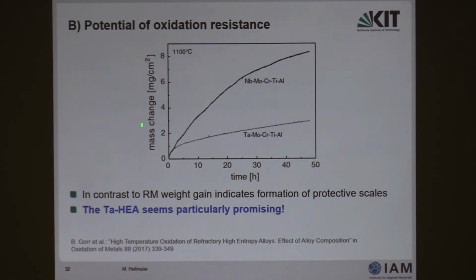We plot this on a quadratic scale. So it's delta m square, so the mass change per unit area to the square, over time linearly. And then you would see that both of these alloys show a linear behavior. And this is an indication for a parabolic growth law. And again, this is another indication that the oxide is protective. You can also have much stronger increases, linearly, for example. Linear oxidation would mean if I double the time, I have twice as much mass change. Or in other words, twice as much metal consumption in the same time.